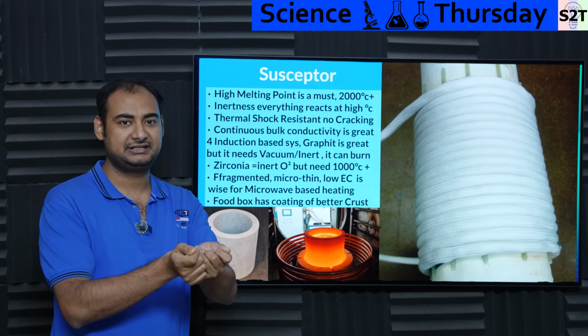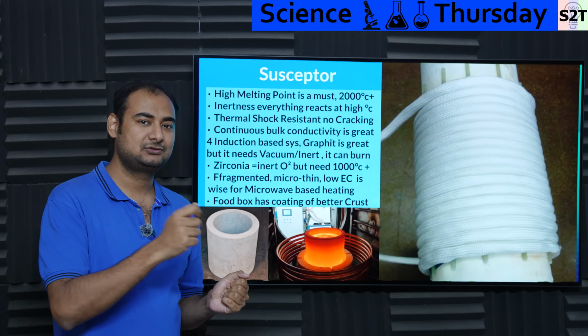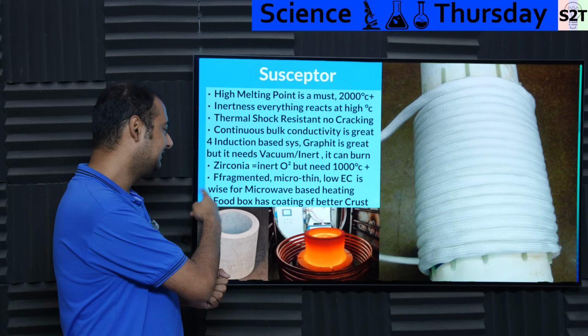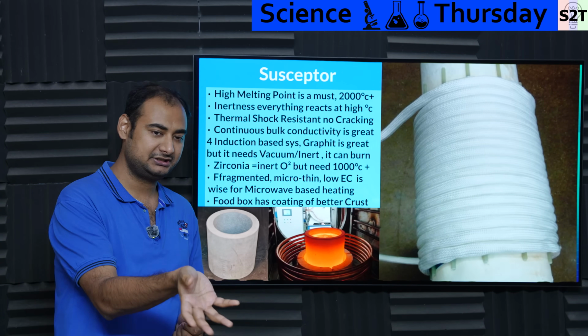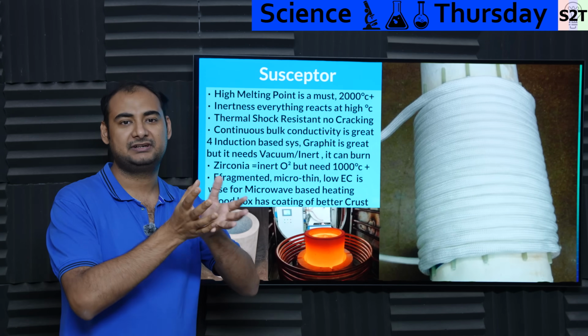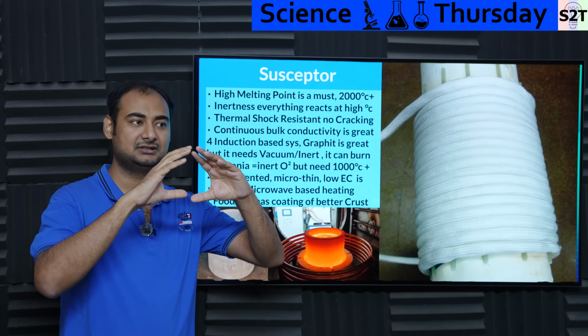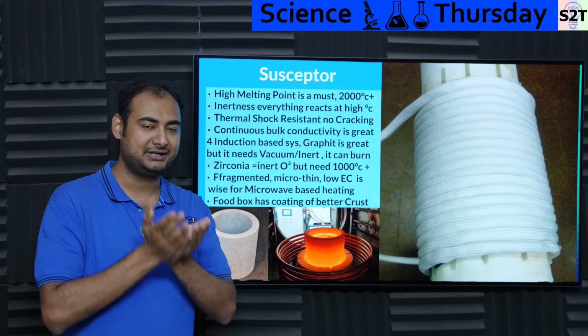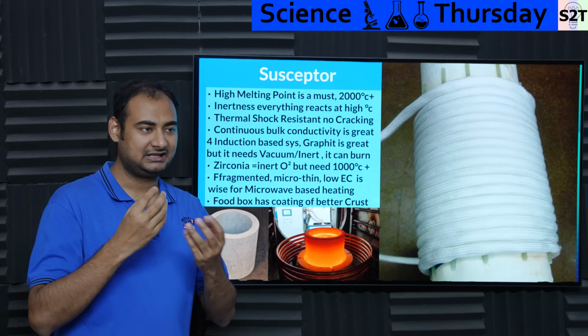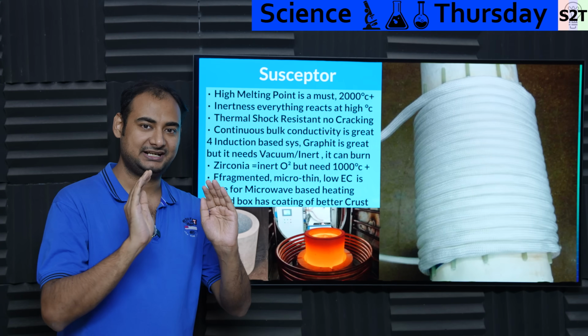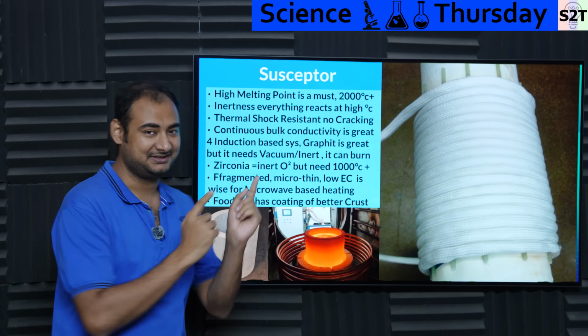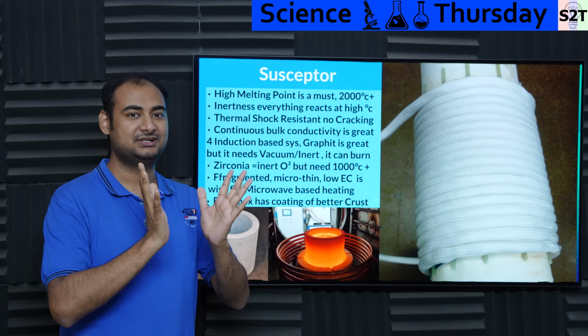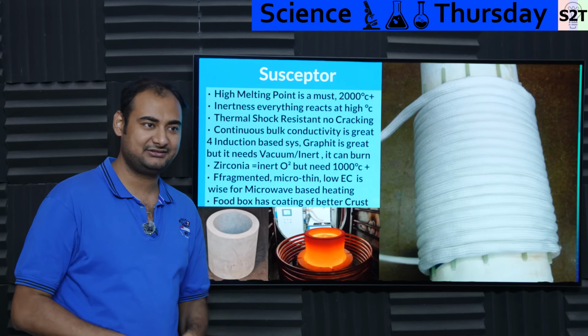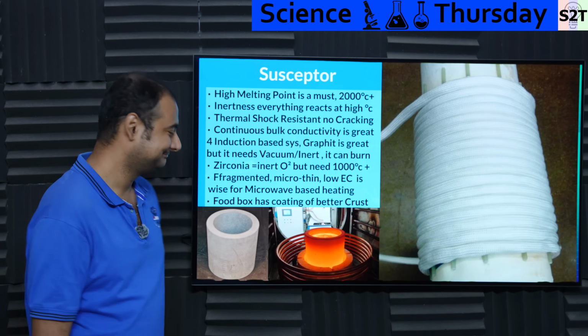If they say please cook in the package, that simply means it has a susceptor coating in it. You put it in a microwave, and the microwave reacts very well with water. Let's say you have to make what we call choco lava cake. The cake outside must be cooked via infrared, but microwave only melts the inside. You will have that very soggy experience at that point. So the idea is the cup has this susceptor. The cup cooks it. Physically, it absorbs the microwave and heats up. So you are cooking the outside with infrared and the inside with microwave. Tada, choco lava cake.